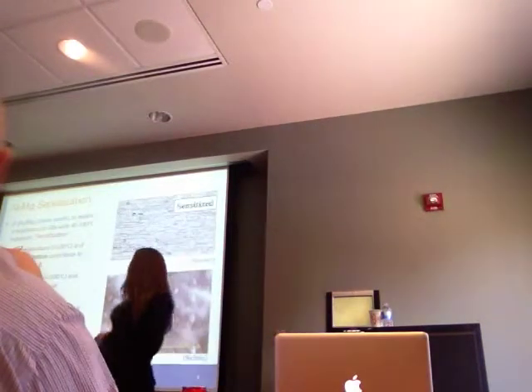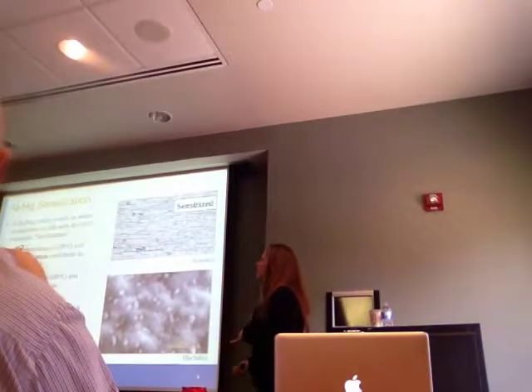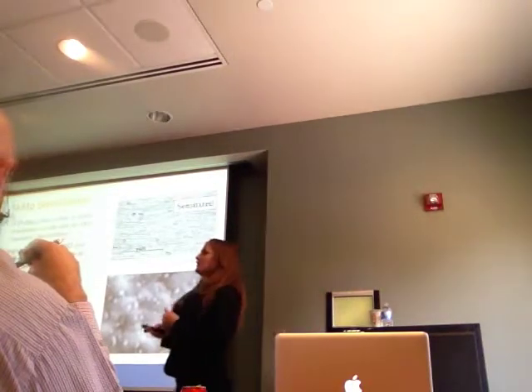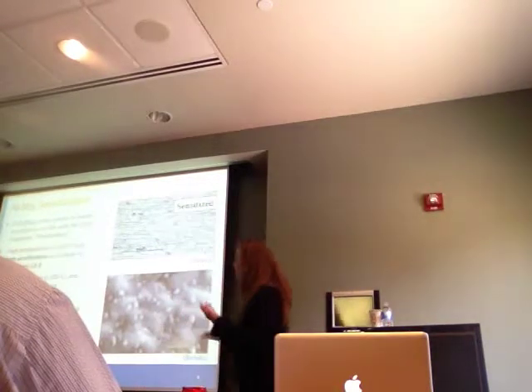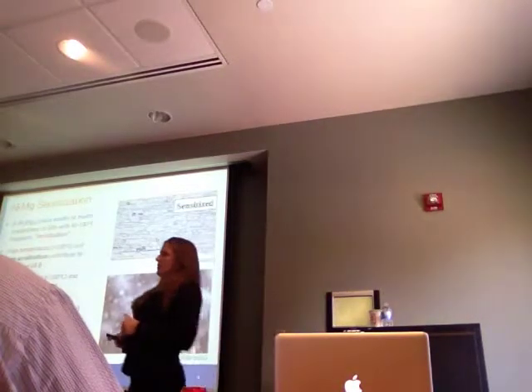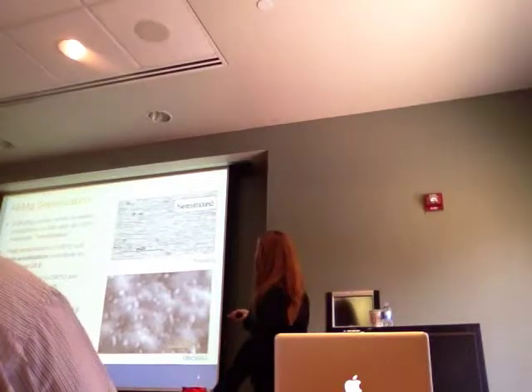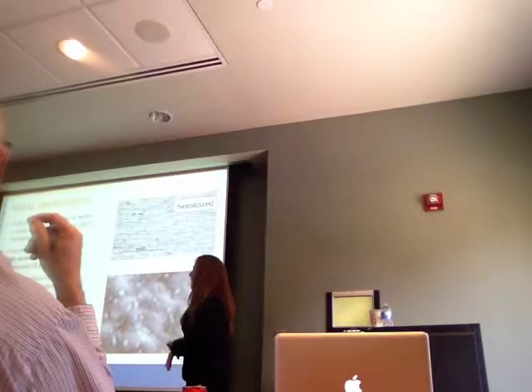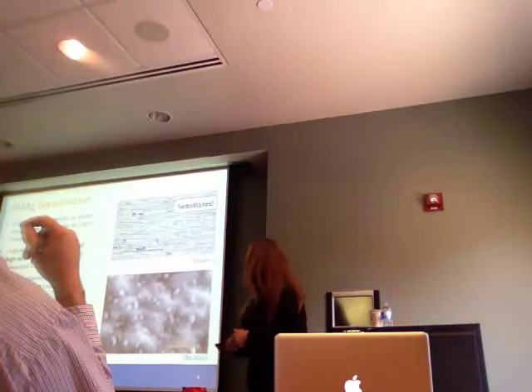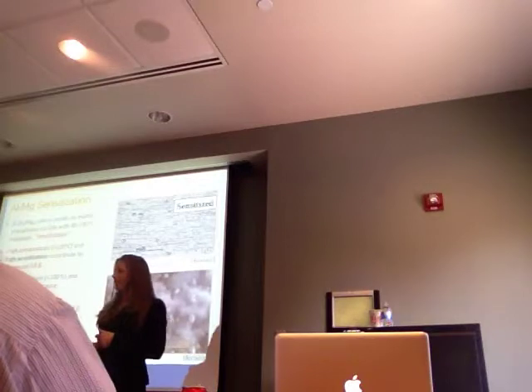Now, we like to use high temperatures because that's easy to cause sensitization in the lab. The problem is when you sensitize at temperatures above 100 degrees C, you'll get a connected grain boundary beta morphology. Something that looks like this. All of your grain boundaries are coated in this beta phase so that you have a very easy crack path that's continuous, well, semi-continuous, for intergranular corrosion and intergranular stress corrosion cracking. So what we wanted to focus on was low temperature sensitization, where you'll have a more discontinuous precipitation of the beta phase. And so that might look something like this on the grain boundaries. You have these small particles that are separated, and these could cause a different mechanism for intergranular corrosion and intergranular stress corrosion cracking. So the connectivity and the distribution of beta is what controls intergranular corrosion and stress corrosion cracking, and it has not been investigated.